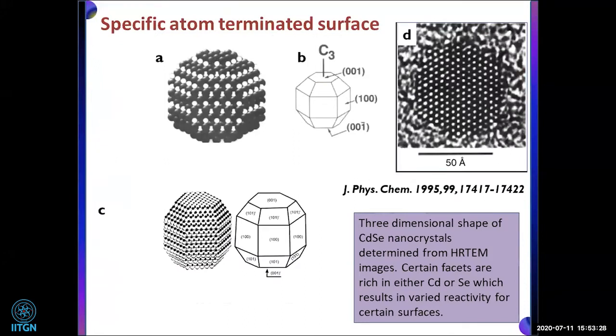Coming to the preferred sites, the specific atom terminated surface is a very popular phenomenon. I'm taking an example from a very famous paper on cadmium selenide nanocrystal. This is the high resolution image of this cadmium selenide nanocrystal. You can see here there are three facets: one is 0, 0, 1, one is 1, 0, 0, and one is 0, 0, minus 1. In this one, the top surface is selenium terminated, and the bottom one is the cadmium terminated surface. Now, cadmium selenide is not a good catalyst.